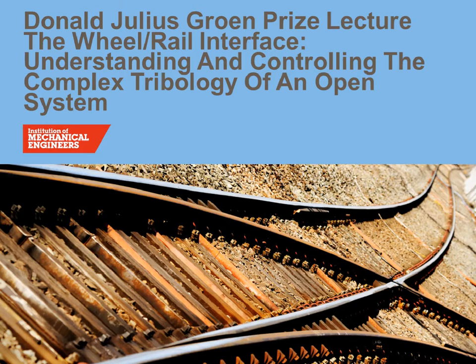This is a really interesting question, and I think we'll probably find out more about that as we move into doing some field tests to see how the clad layer responds under realistic wheel loading and in the open environment. One thing I should probably note is that we're thinking that the current damage models that are used for predicting what will happen to rail materials aren't now all that appropriate for the kind of materials we're cladding, as they're so hard, and because they don't plastically deform. A lot of the models rely on that kind of deformation process to allow the damage prediction. So it may be that we need to introduce some new approaches to predicting what will happen to these harder materials.